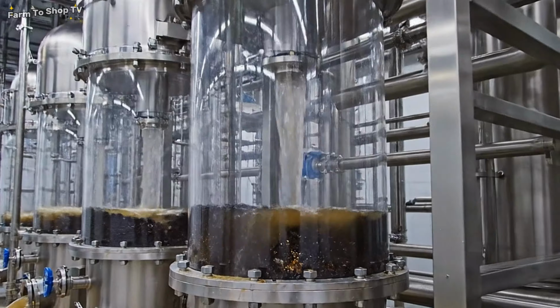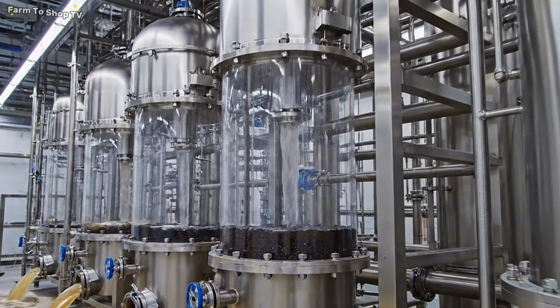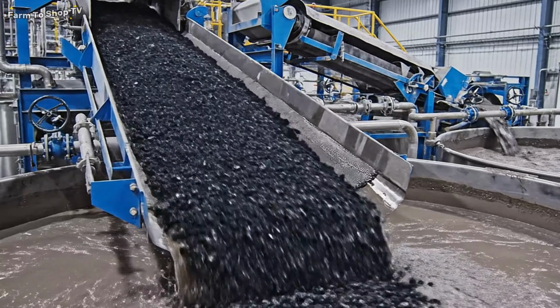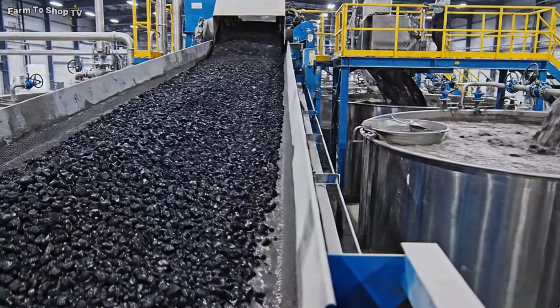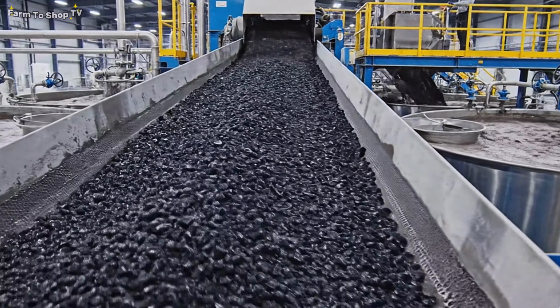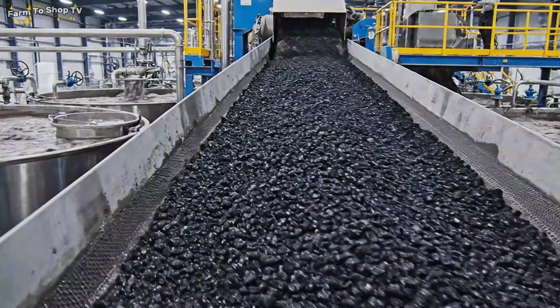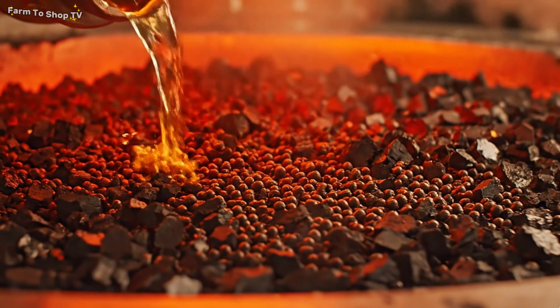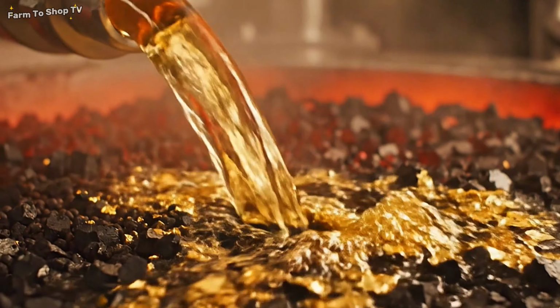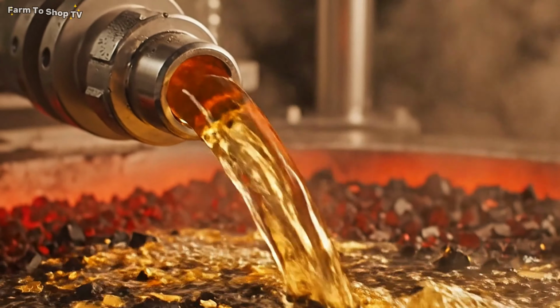As the solution continuously moves through the columns, the gold is adsorbed onto the carbon. This is the carbon separation stage. The loaded carbon is filtered out of the slurry using this vibrating screen. Here in the desorption chamber, high temperatures and a pressurized solution cause the gold to finally detach and dissolve from the carbon.